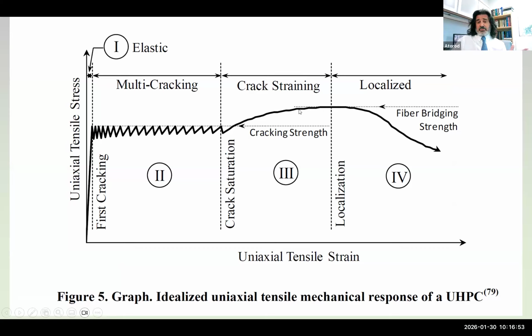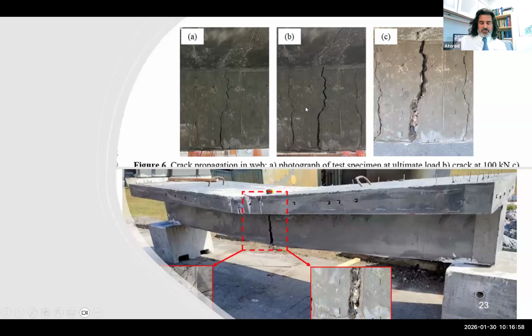And that's when we calculate. We say that's the capacity of the section. I can show you here, for example, this beam that we wrapped with UHPC. First, when you load it, you get multiple cracks. Then one crack located at the maximum moment point takes over, basically opens up. Once that big crack, or crack localization, takes place, the other cracks don't open up. And at that point, we say that's the ultimate capacity of it.